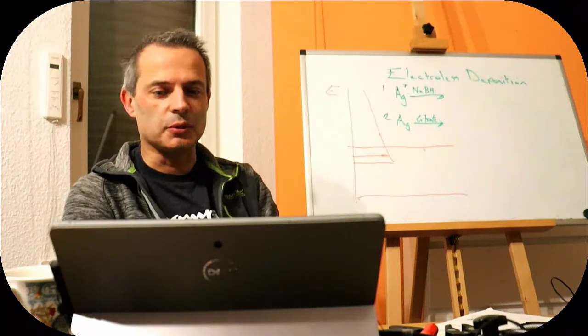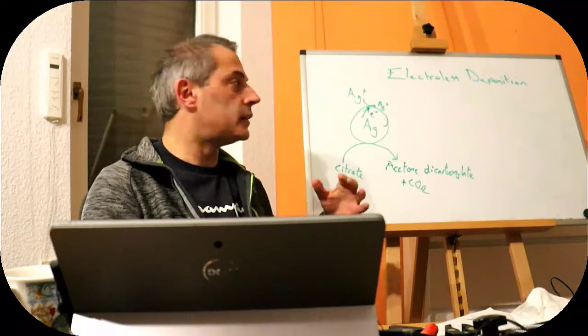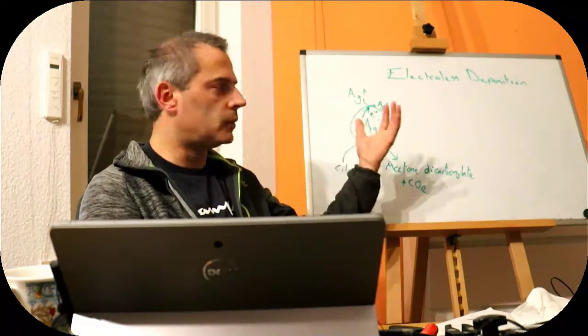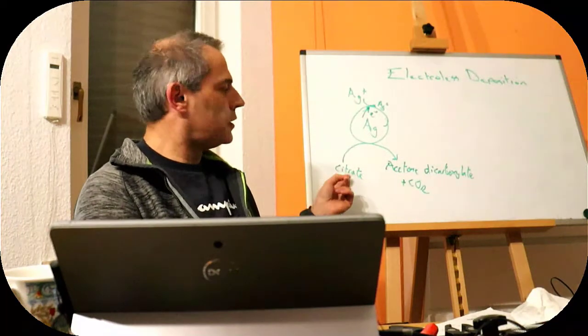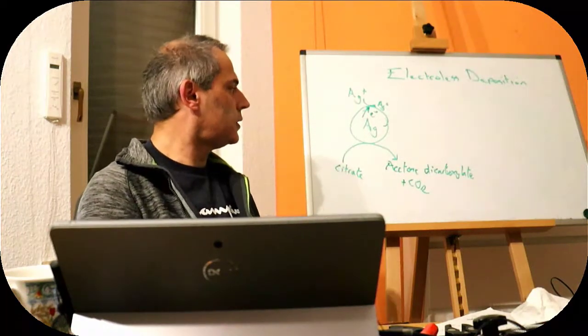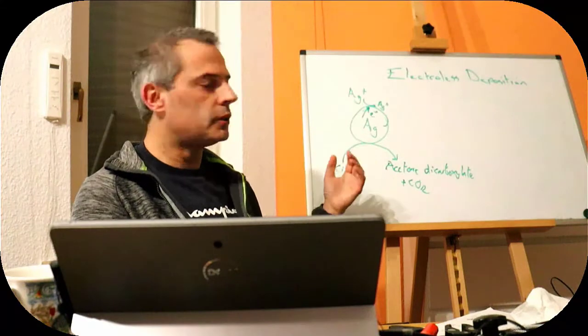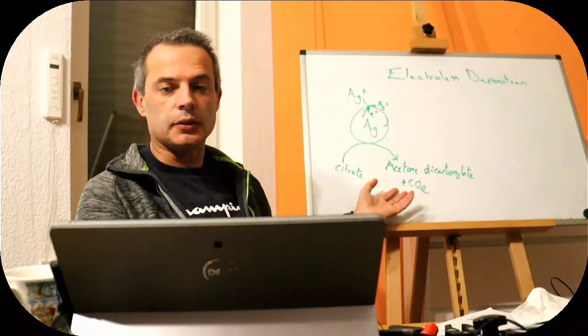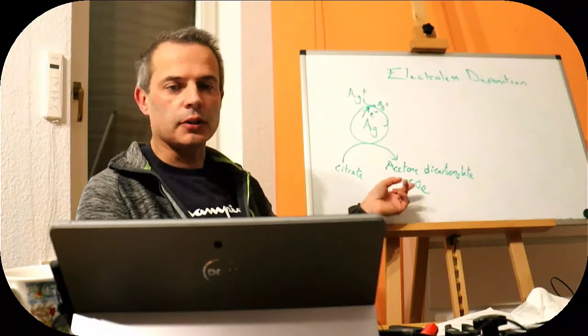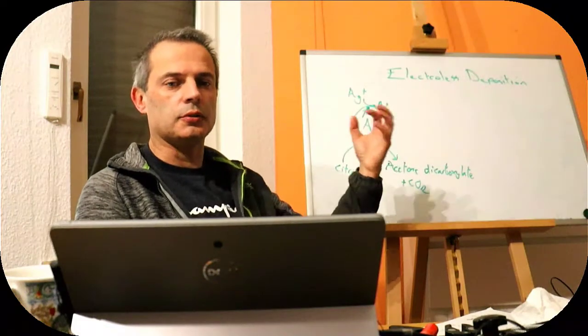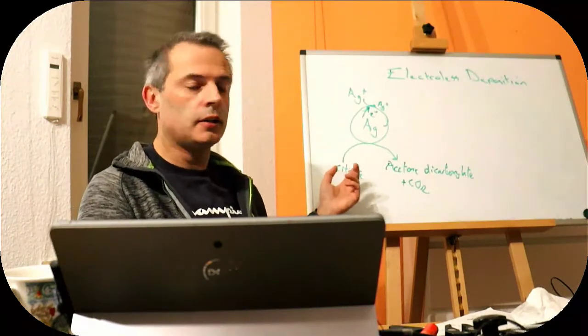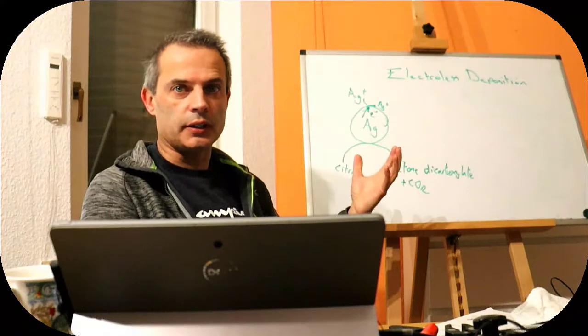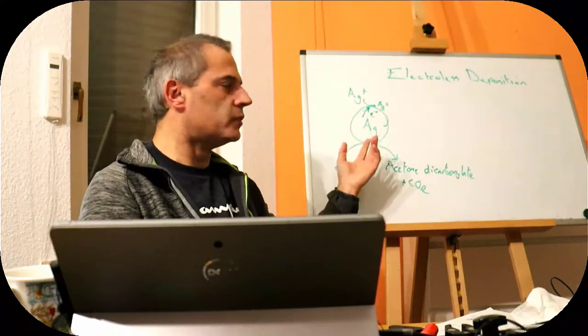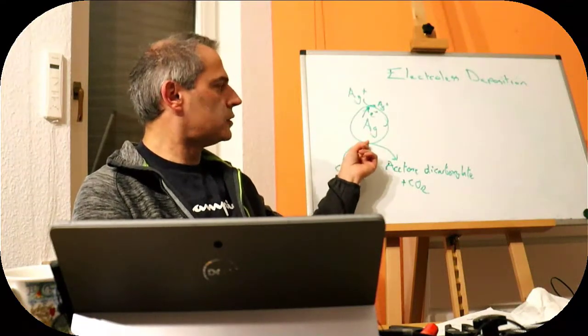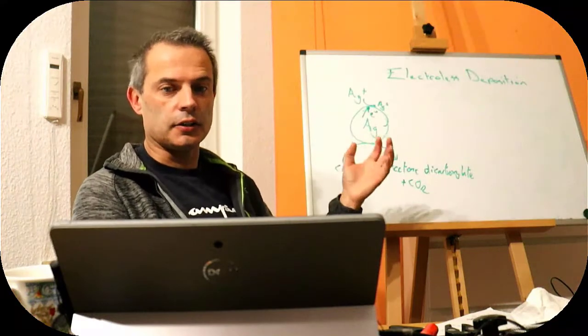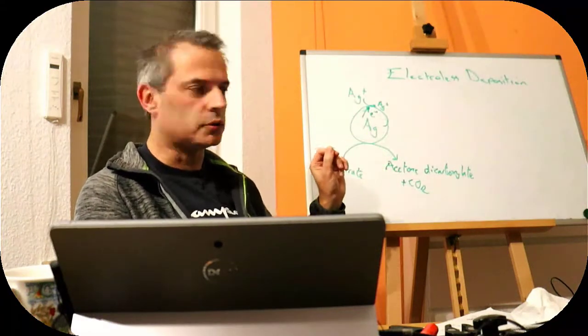I hope that's understandable. So here is the reaction at a silver particle. It's easy at a silver particle. The citrate anion is oxidized to acetone dicarboxylate plus carbon dioxide, so a CO2 group is split off the citrate anion. That is relatively complicated to do, so it requires lots of moving of bonds and things, and so that is easier at a surface where we can form temporary bonds to the surface.